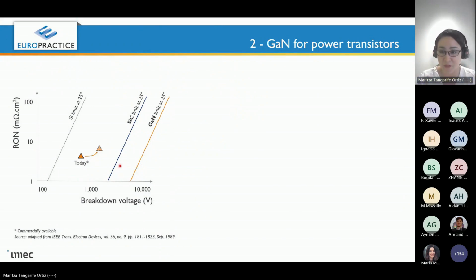Okay, I was saying that there are benefits because there is a relationship between the breakdown voltage and the R-on of these materials. As we see in this figure, we have the theoretical limits for this relationship for silicon, GaN and silicon carbide. We can see that for a given breakdown voltage, the R-on of these materials is much lower than for silicon. And GaN is the lowest of the three. Silicon has basically reached its theoretical limit. The use of GaN and other wide bandgap materials has become necessary to improve the R-on.